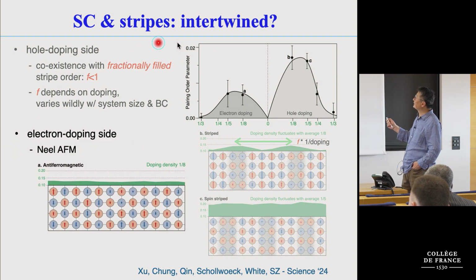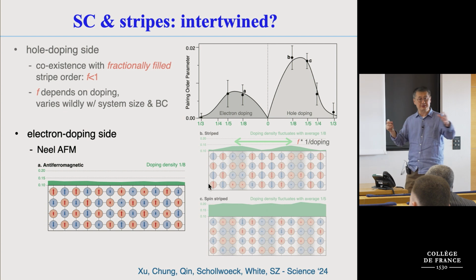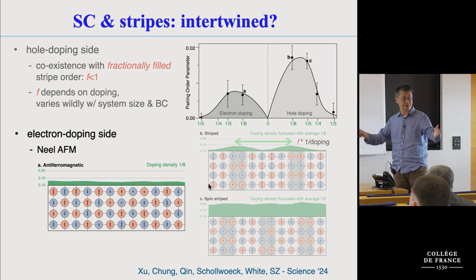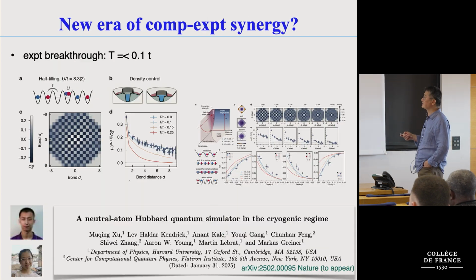And on the electron-doped side, we see Néel antiferromagnetism, which is also sort of consistent with the cuprate phase diagram, although we seem to be seeing a coexistence, which is a little inconsistent with the experiment.